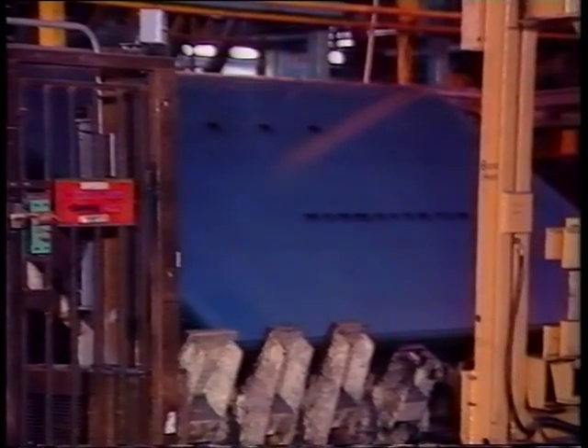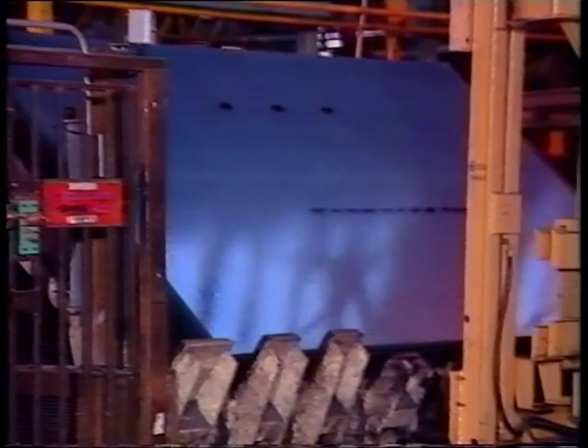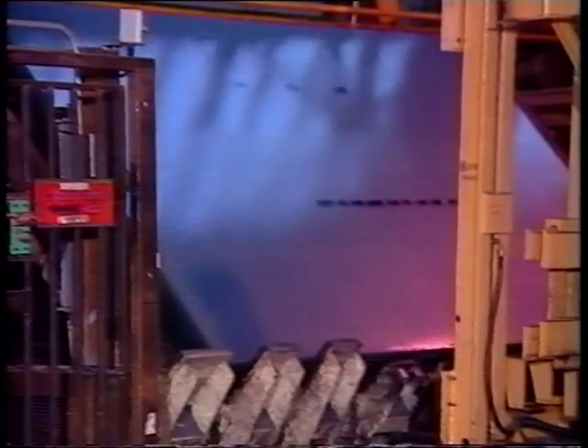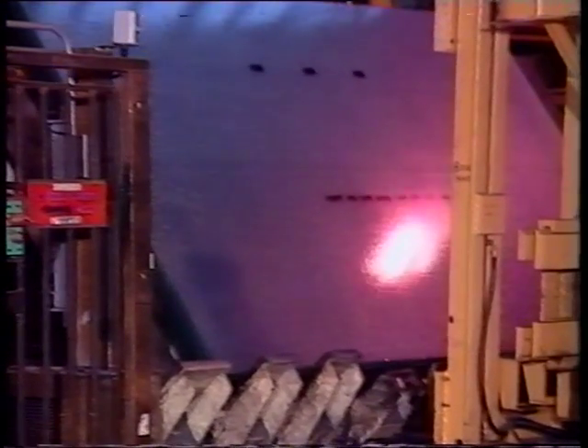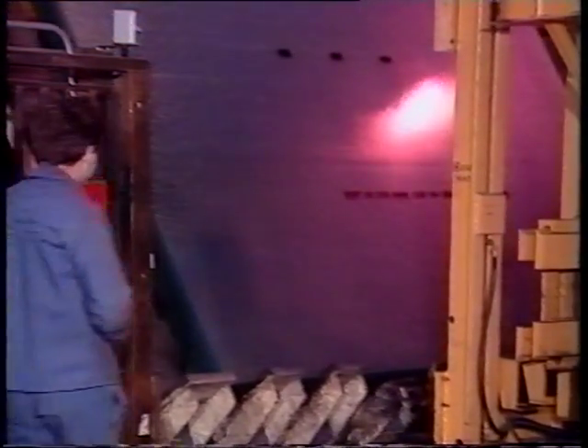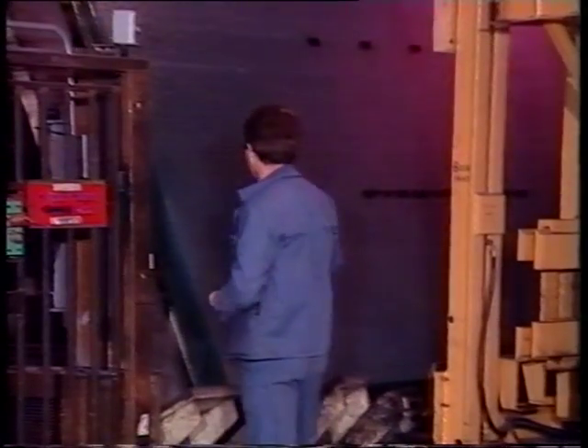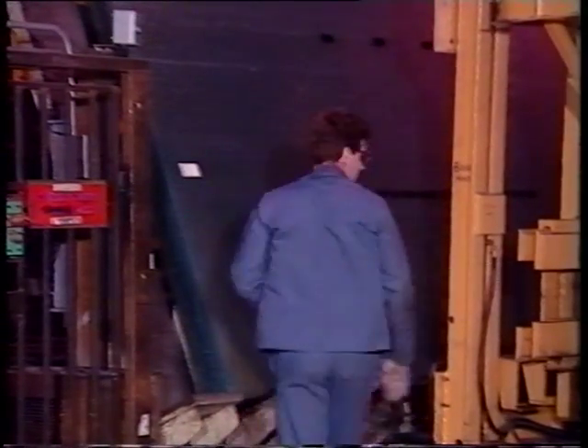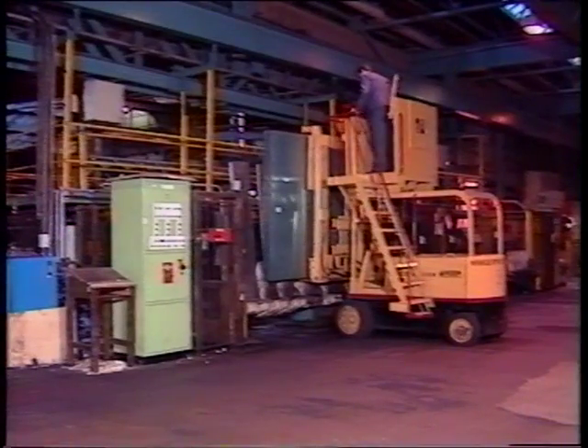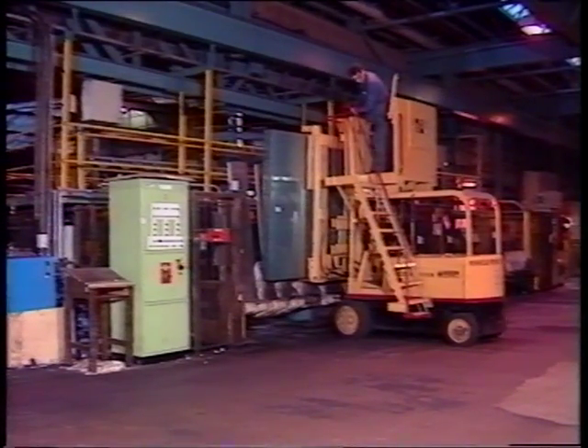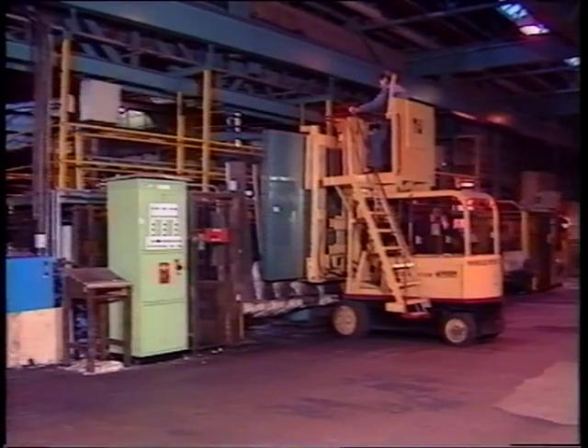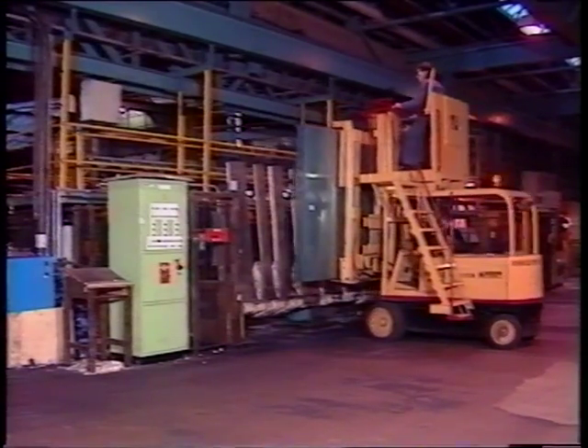After breaking out the plates, the glass is examined before the plates are made into packs. These are made up by using horizontal stacking equipment, and packs containing 19 plates are assembled by this means. After pack making, the glass is transferred into the warehouse stocking areas, where it must stand for at least 12 hours before dispatch to Doncaster.